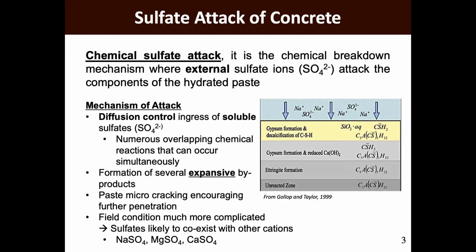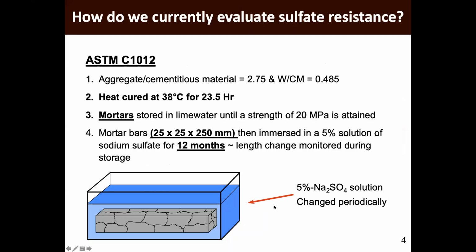really a severe form of deterioration, depending on the concentration and the type of sulfate. The most common ones we typically refer to are sodium, magnesium, and calcium sulfate. The method we currently use to test for sulfate is ASTM C1012. This is a performance method that uses mortar bars with a high water-cement ratio, about 0.485. You heat cure these samples, and then you simply place them into a 5% sodium sulfate solution.